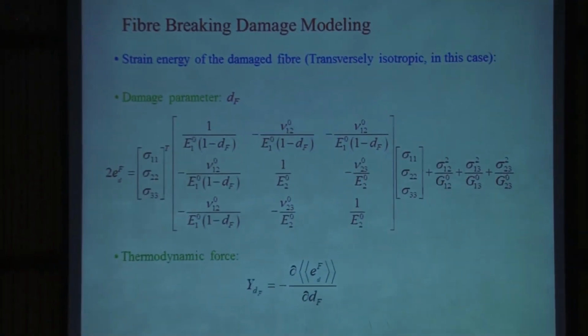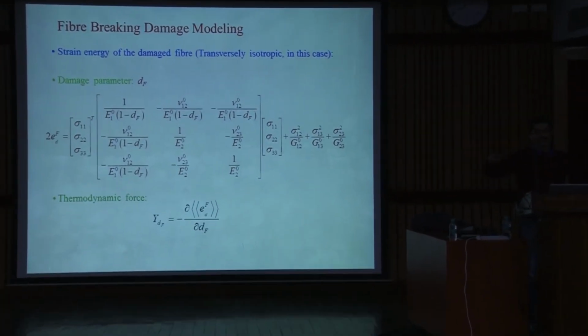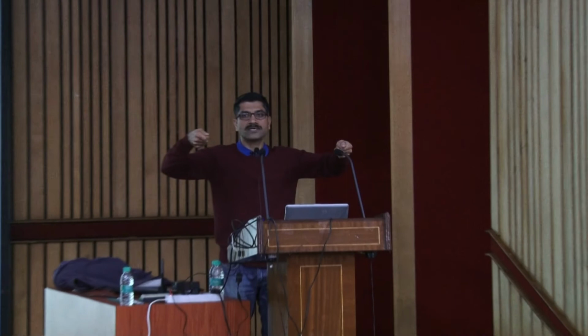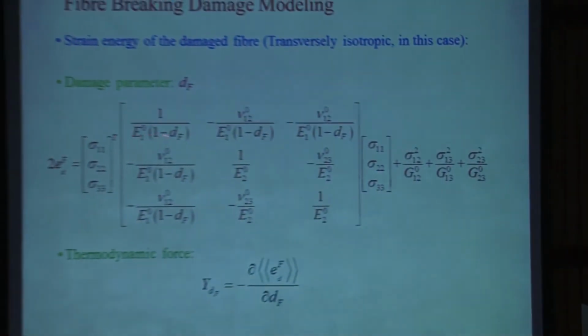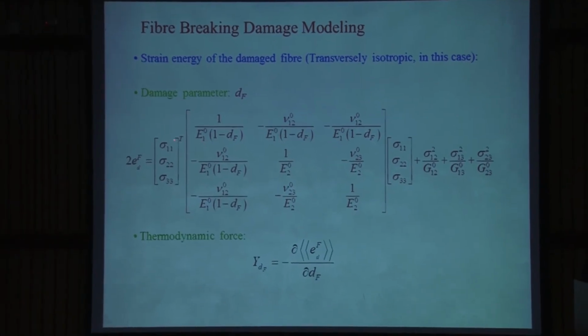So, this is one of the important failure mechanisms. One more assumption is that when you are considering the fiber failure, it will affect only the modulus in the fiber direction. Its effect on the other direction is lesser. If the fiber is broken, then it is almost a catastrophic failure. So, there is no chance that you will have some failure in the other direction and then this will fail. Okay. So, the assumption is that if the fiber is going to fail, it is going to affect only the stiffness in the fiber direction, that is direction E1.